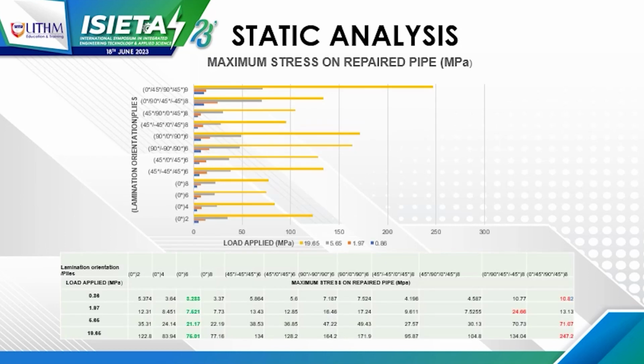This is the static analysis that we generated from the simulation. As we can see, on the left is the lamination orientation, from 0 degree until 0, 45, 90, 45 degree with 8 plies. Then the maximum stress generated for each lamination orientation, with 4 loads applied constantly, which are 0.86, 1.97, 5.65, and 19.65 megapascal. The lowest we got is for the lamination orientation of 0 degree with 6 plies, which shows the lowest stress, 3.283 megapascal for 0.86 megapascal. When a load of 0.86 was applied, 3.283 megapascal was shown as the maximum stress. It is the lowest for every load applied.